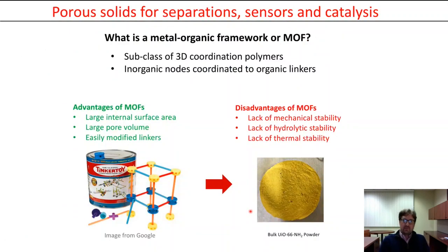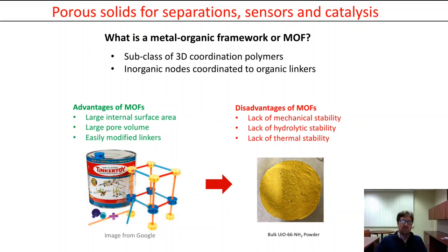If you're not familiar with metal organic frameworks, that stands for a MOF. It's essentially a type of three-dimensional coordination polymer with alternating inorganic ions and organic linkers. This Tinkertoy image gives you a general idea of what a MOF really is — the struts represent an inorganic ion and the sticks represent a bifunctional organic molecule. This repeats in three dimensions, so think of this as just the unit cell. The Tinkertoy image conveys the very large internal surface area. You can change the length of the linker to change the pore size, and put functional groups pointing into the pore to control the chemical and physical properties.